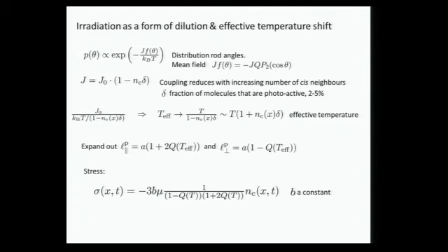And if I do that, I get the stress is proportional to the energy scale, the shear modulus, a constant B, which says how quickly the step lengths vary with changes in the order parameter, and how quickly the order parameter changes with a change in temperature, and then the essential part of the temperature change appears here, the cis concentration.